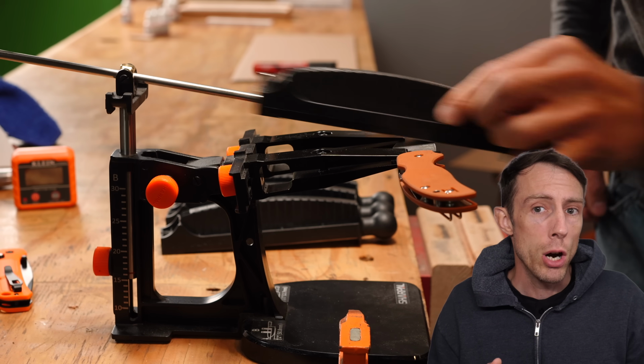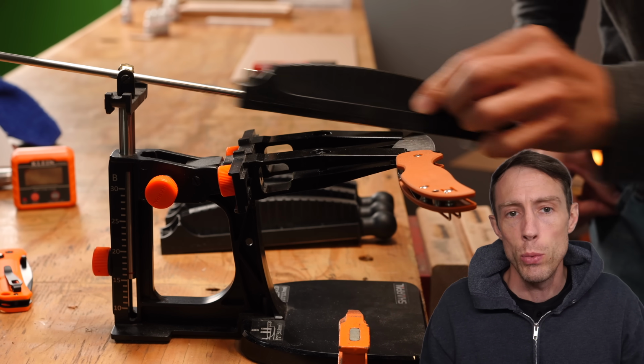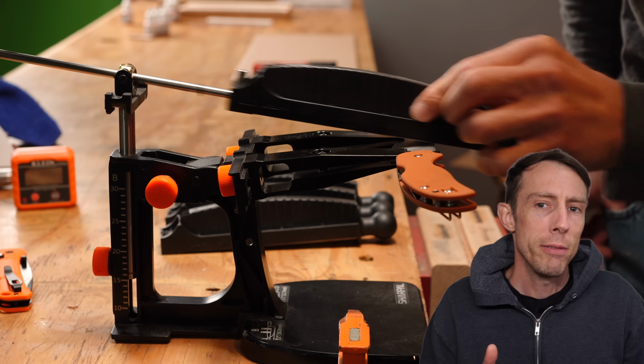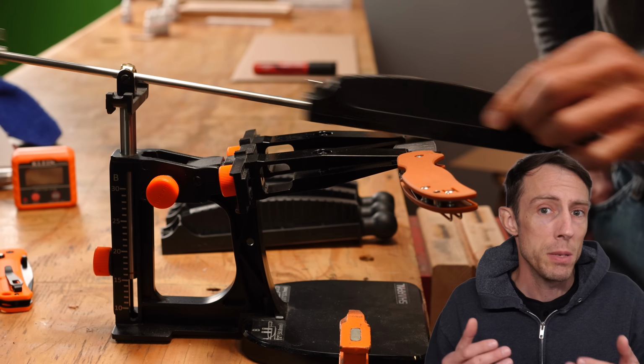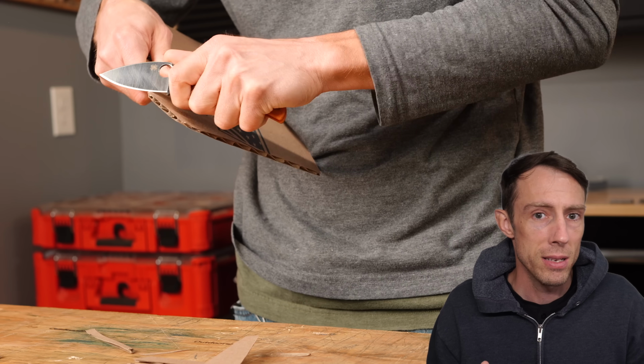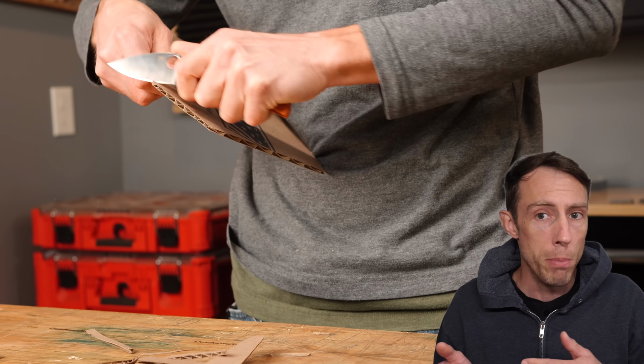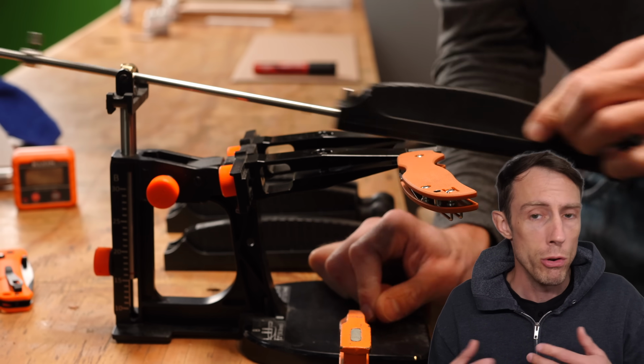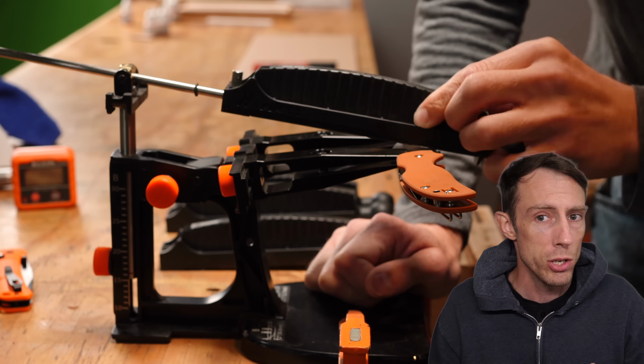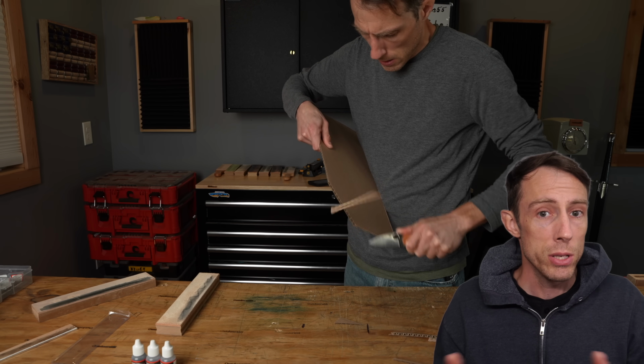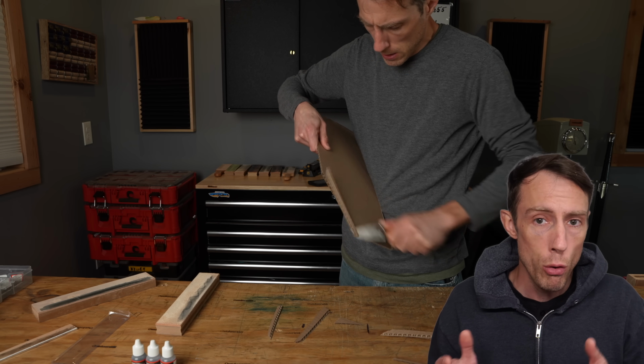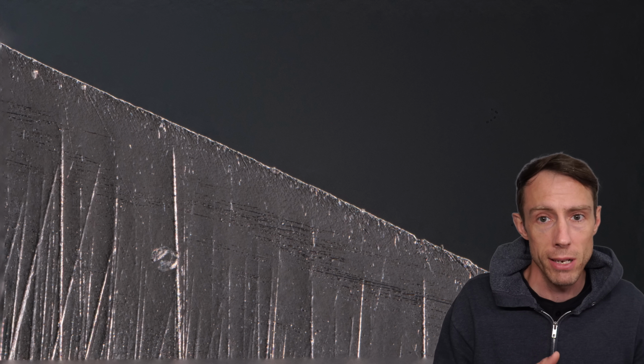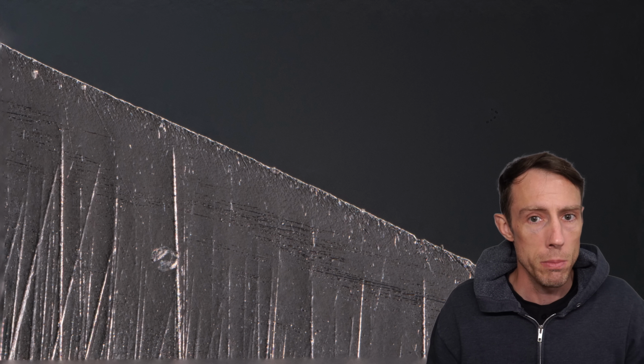Now I immediately resharpened the edge to start doing some testing with known geometry. But I ran into a problem. That problem was that I experienced some chipping issues doing some very basic cardboard cutting tasks. I ended up reprofiling to a bunch of different angles until finally, after removing quite a lot of steel, I mean a bunch of steel, reprofiled a bunch of times, the chipping issues somewhat subsided, and I was able to finally go back and reprofile again to 17 degrees per side with minimal chipping issues.